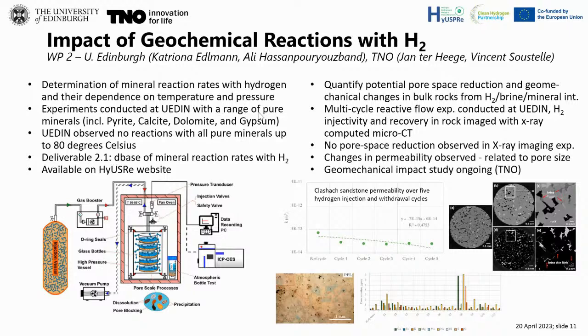On the right here, there is another task, quantifying the potential pore space reduction and geomechanical changes in bulk rocks from hydrogen-brine-mineral interaction. Edinburgh did multi-cycle reactive flow experiments, conducted with hydrogen injection and recovery, and imaged the rock with X-ray computed micro-CT. Also there, they did not really observe any pore space reduction in the X-ray imaging experiments. They did observe changes in permeability related to pore size. The geomechanical impact specifically, so how does the exposure to hydrogen impact the geomechanical characteristics, is ongoing. This is work done by TNO by measuring geomechanical properties of the exposed rock samples. This is work in progress.